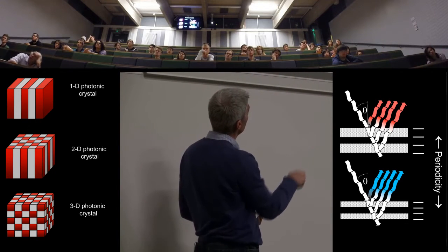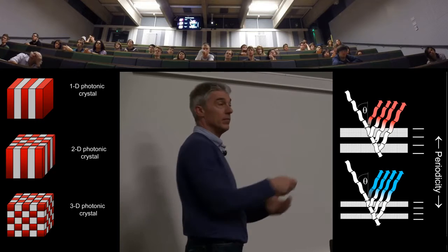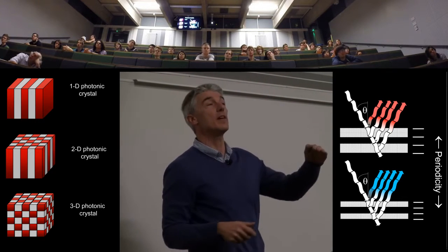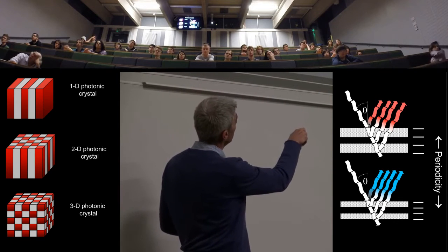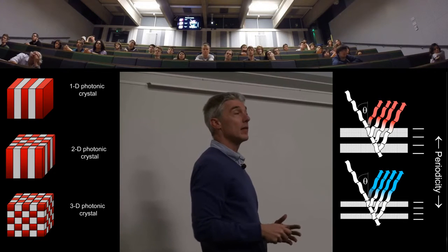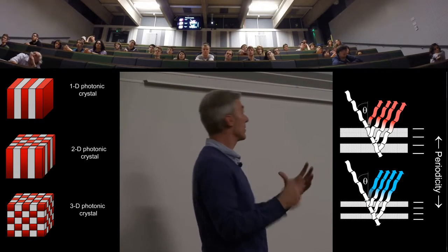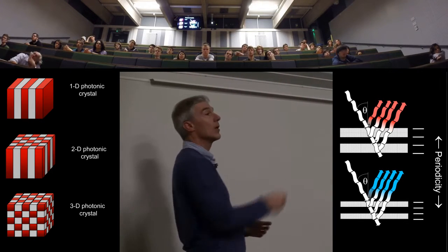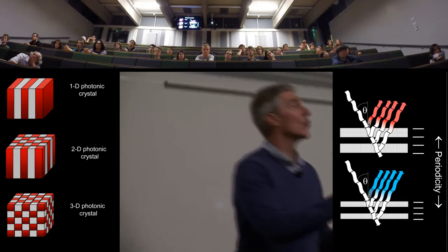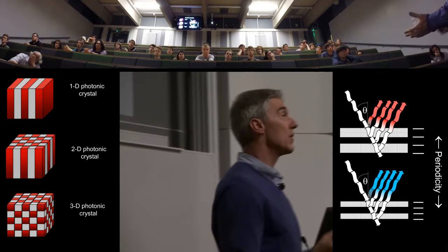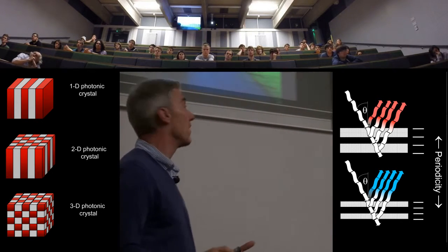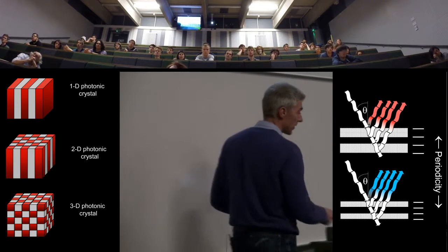With an appropriate thickness, with an appropriate, let's give it a label, this periodicity, this spacing between interfaces. If they are regular, and if the angle is right, and the refractive indices, A and B, are appropriate, we will get strong constructive interference in reflection for one wavelength, strong constructive interference in transmission for another wavelength. And it gives rise to very strong color effects.